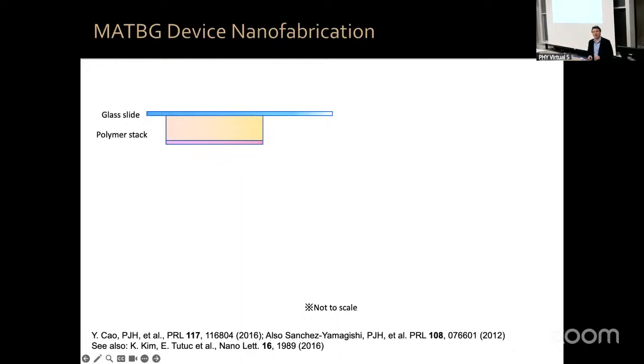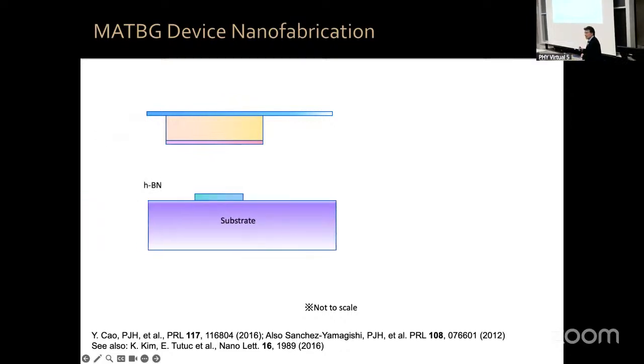We start with a glass slide, a transparent glass slide with a polymer stack, and at the bottom there's a sticky polymer. Then we bring a substrate which has a hexagonal boron nitride flake on it. For the first half of this talk, boron nitride is just a high quality dielectric insulator that does nothing—it just helps maintain the pristine properties of graphene. We'll see in the second half that you can do a lot of stuff with boron nitride, but for now, it's just an inert high quality substrate.